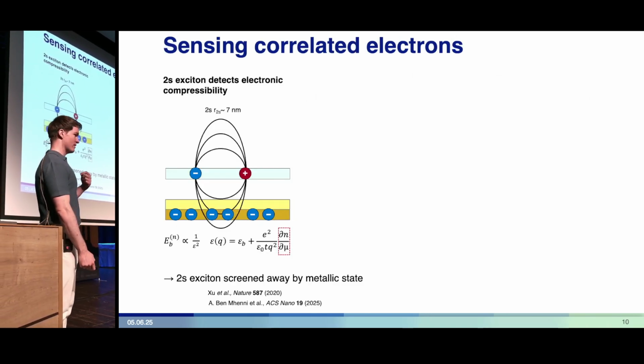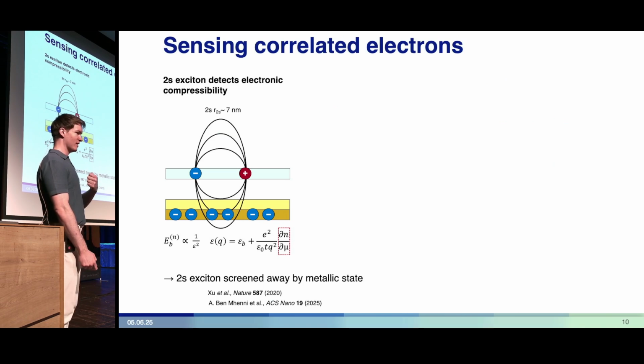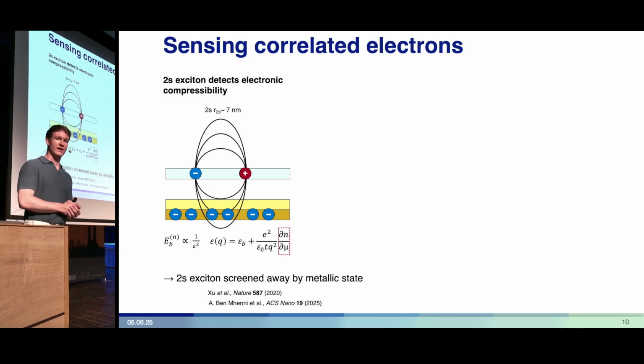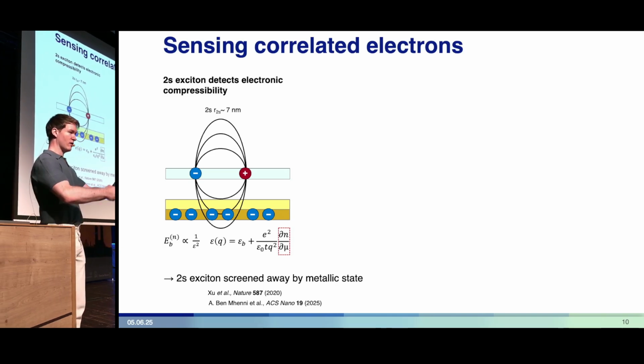It turns out that the most useful exciton to study electronic correlations in the bilayer electron system here is the 2s exciton residing in the monolayer WSe2. It's a bound electron-hole pair, the excited state of the neutral exciton. What's important about it being an excited state is that it has a relatively low binding energy and a relatively large radius.